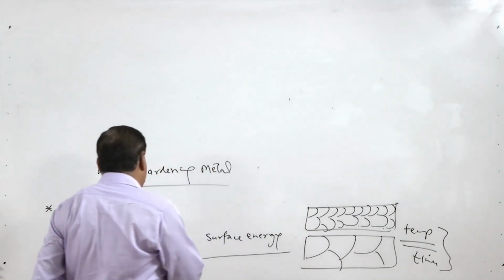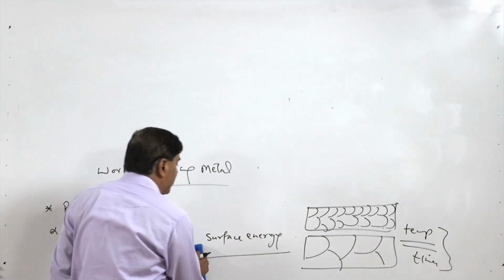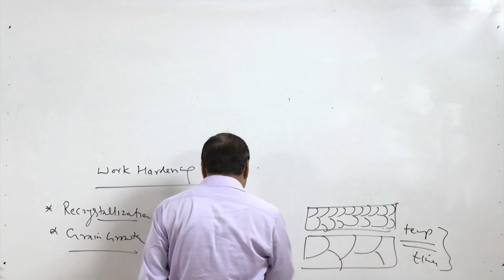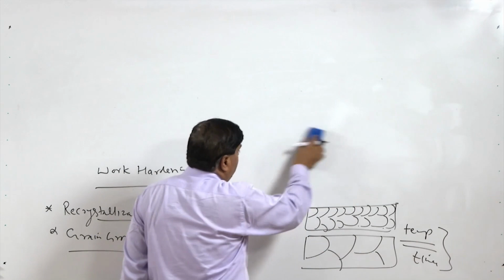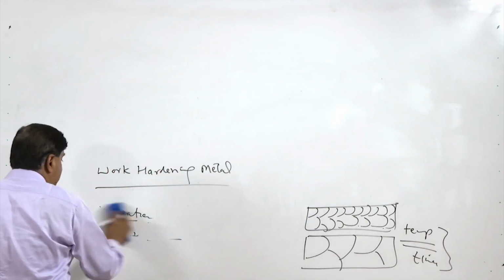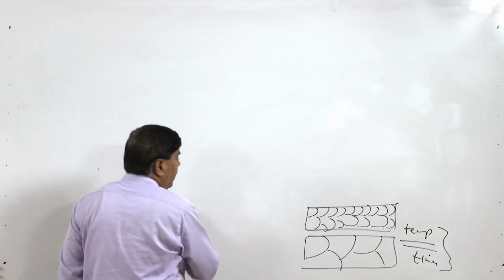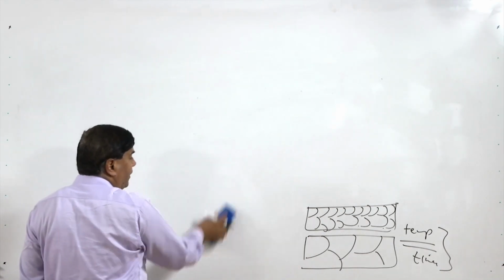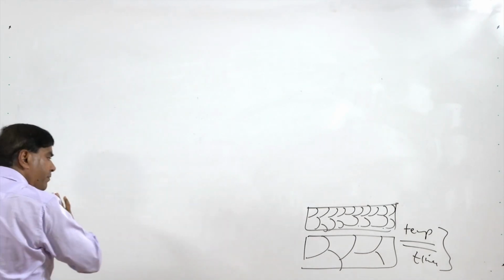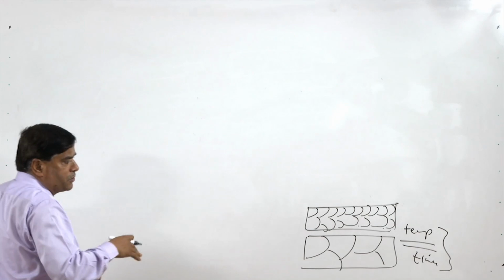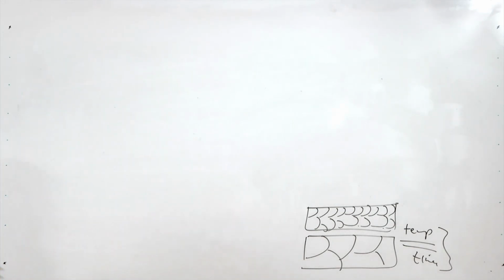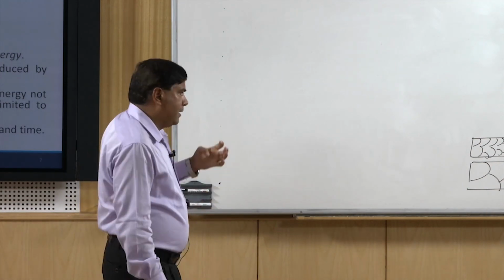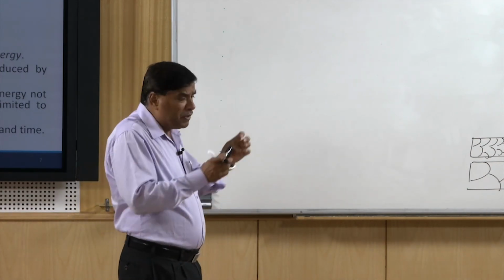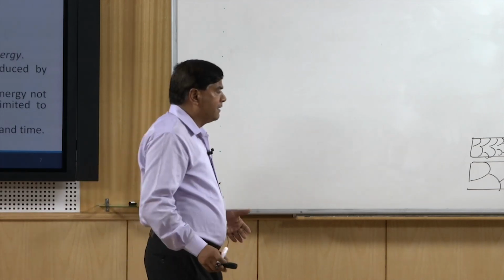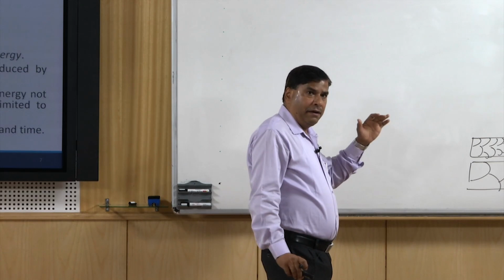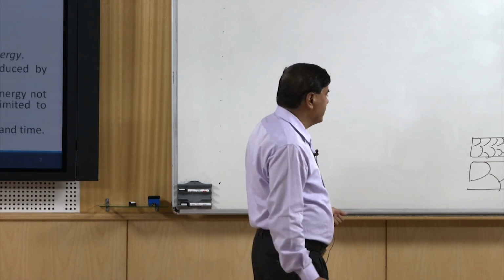Systems tend to reduce their surface energies, and since strain energy does not play any role in grain growth, it is the surface energy that governs the grain growth. Therefore, the grain growth phenomenon is not limited to work hardened materials only, but applies to all kinds of systems. Most metal systems are polycrystalline in structure, and they tend to attain the minimum surface energy by grain coarsening. So, whenever favorable conditions for diffusion exist, with high temperature for sufficient time, it will cause grain growth.